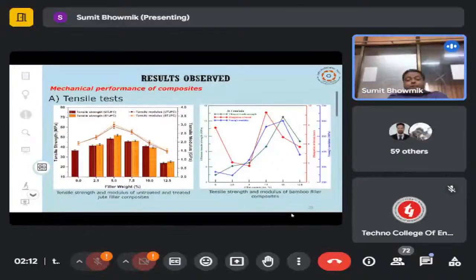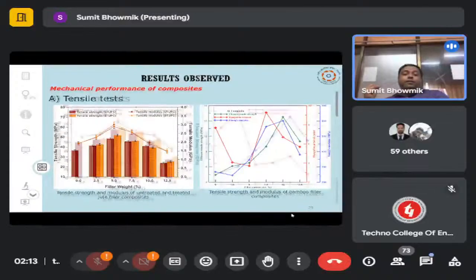Now the question is, why after 10% or 12% is the filler decreasing the property, though it should increase it? But it has been observed from the microstructural analysis and other analysis that after 7.5% the agglomeration occurs, because they are not bonding properly, since the density of the filler content is increasing. There are some spaces generated where the epoxy is not able to enter between the two filler components of the composite, and they are not able to bond properly. So when the load is applied, since they don't have any bonding with the epoxy or resin, immediately it is broken.